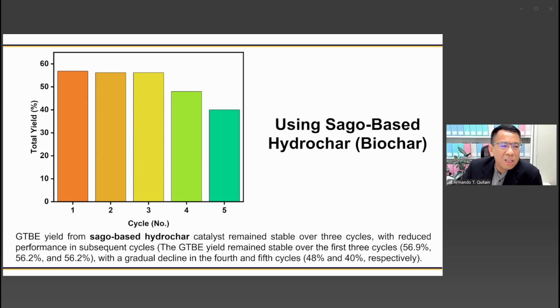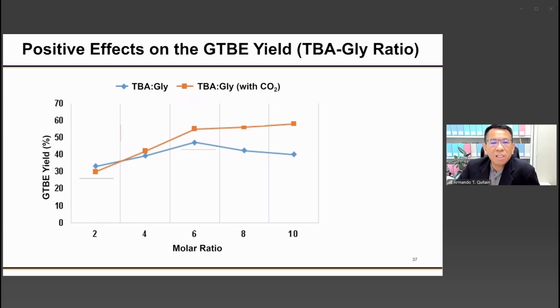Although the total yield is lower than that of graphene oxide, this is still high at about 55%. The functionalities on the surface of biochar are not comparable with those acidic functionalities present in graphene oxide, but still we're getting yield above 50% using sago-based hydrochar. And we even tried pressurizing the system using carbon dioxide. And we also get promising result by pressurizing the system using carbon dioxide and using the biochar obtained from sago biomass.